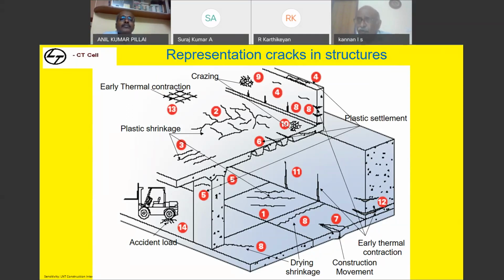But cracks are not harmful in concrete unless they are structural. Okay, so don't jump to conclusions, especially if you are able to take care of the concrete well in the green state, and if you are able to take care of the plastic shrinkage and plastic settlement, 99.99% of the issues in the structures are resolved. Because the majority of issues happen only after deshuttering. We say cracks are there, it has started leaking and all. So kill the crack: allow the concrete to crack in the green state, and kill it with the secondary finish.